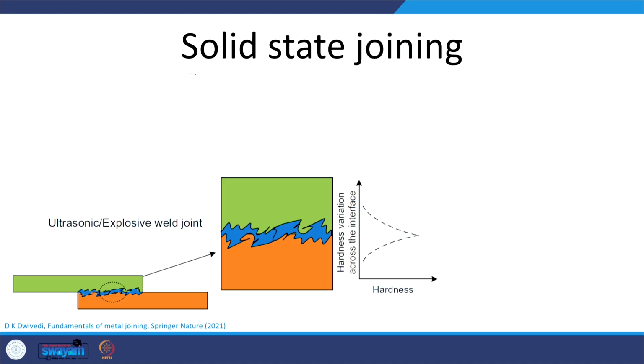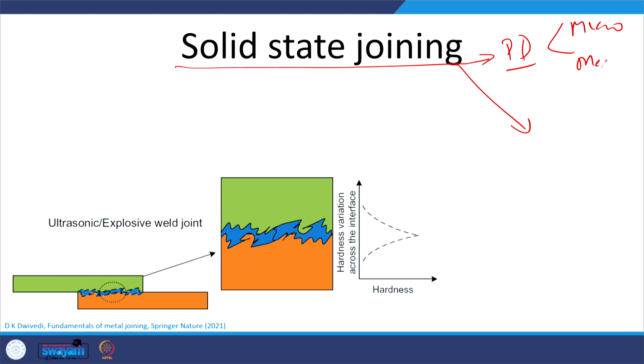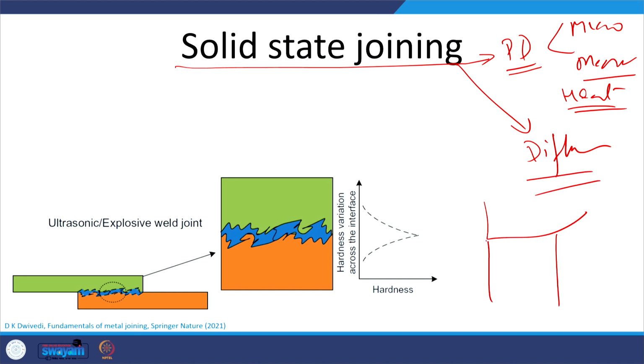Okay. Now, as far as the solid state joining process is concerned, in the solid state joining there are two broad approaches. One is the plastic deformation, which can be both micro or macro level, okay, coupled with the heat generated, which will be causing the recrystallization or the grain growth or recovery or the deformation assisted phase transformation, apart from the grain refinement due to the dynamic recrystallization. That is one thing, where deformation coupled with the heat causes many changes. Okay. Another one is where just the diffusion is involved. Okay. So, like in the diffusion bonding process where primarily at the surface we may have micro level plastic deformation, but mainly the diffusion across the interface is responsible for the development of the joint.